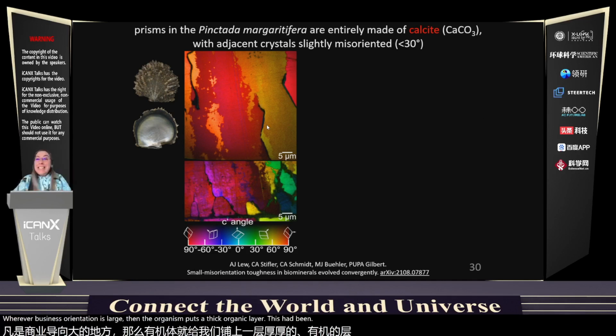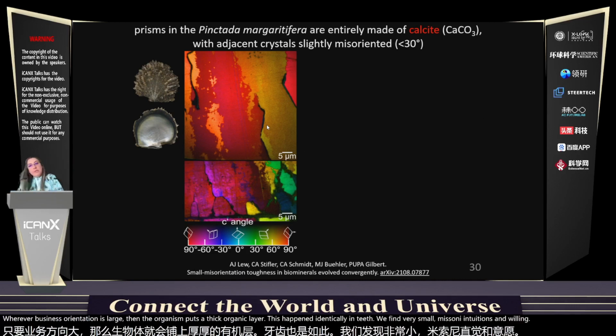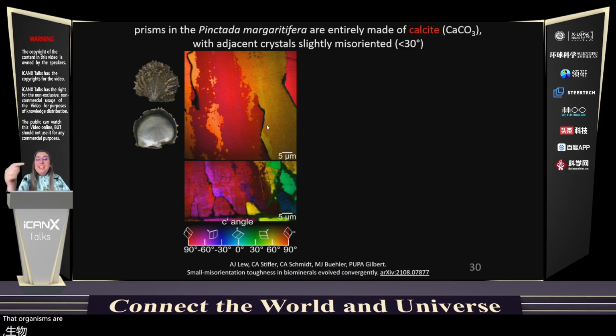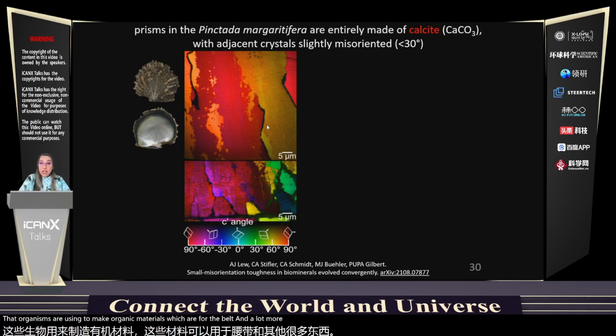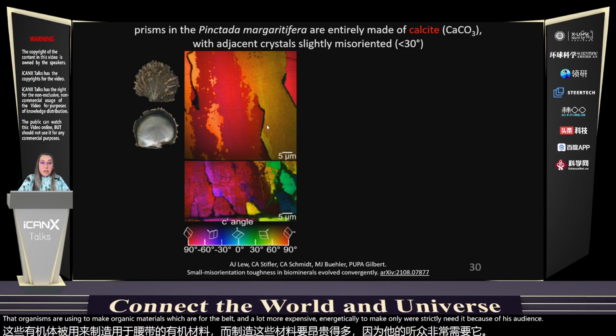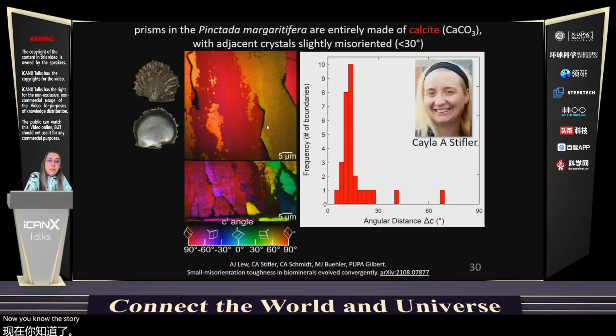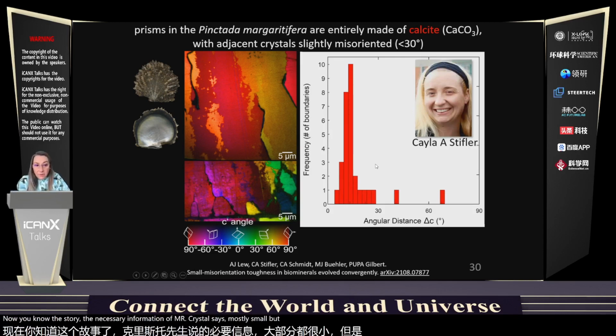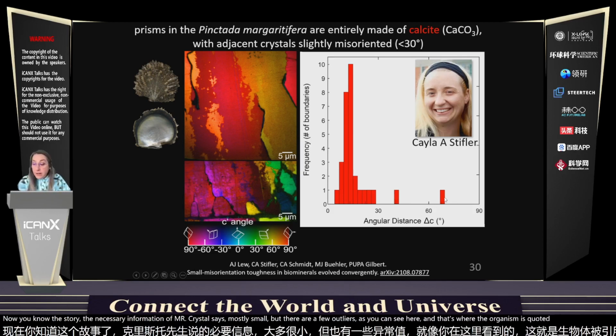This happened identically in teeth. We find very small misorientations, and whenever the misorientation is large, there's an organic layer. So this is a shortcut that organisms are using to make organic materials, which are for them a lot more expensive energetically to make, only where strictly needed because the misorientation is large. Now you know the story. The misorientation of these crystals is mostly small, but there are a few outliers, as you can see here, and that's where the organism is putting the organic layers.